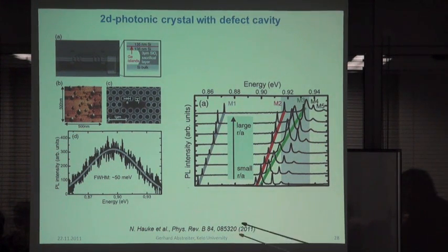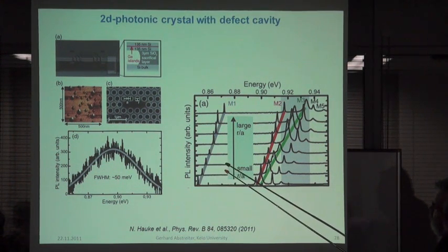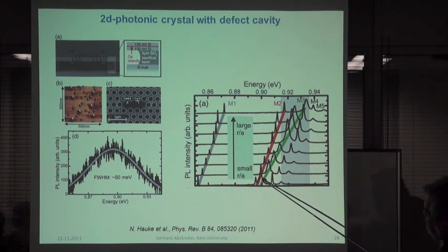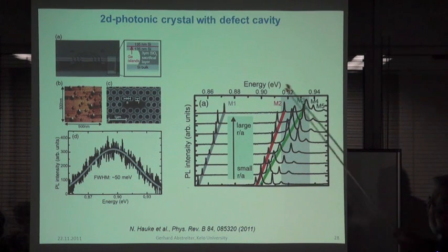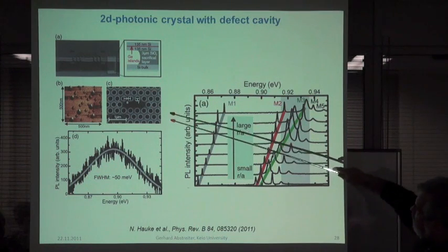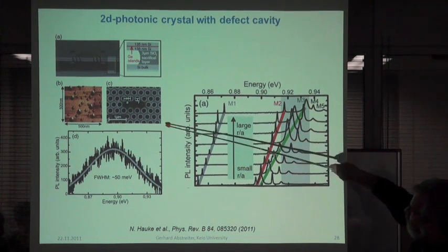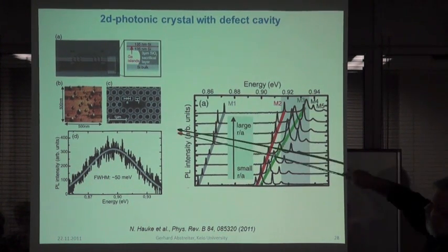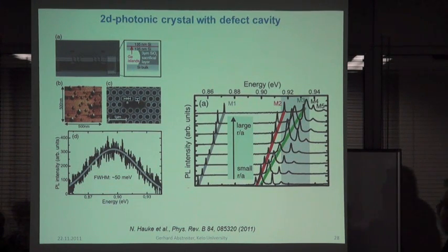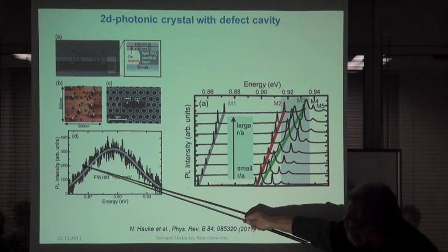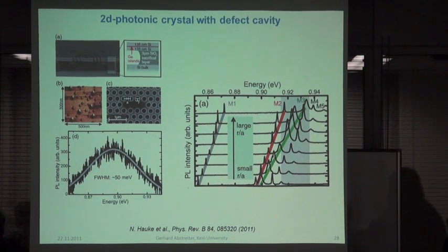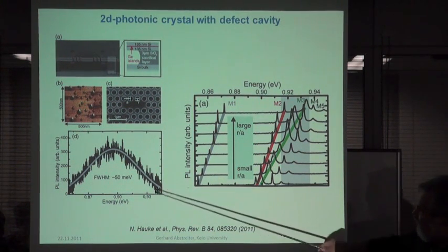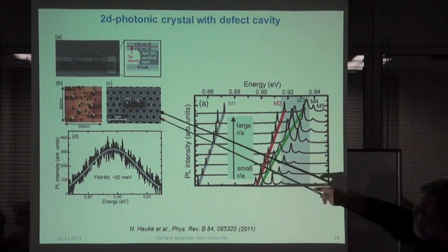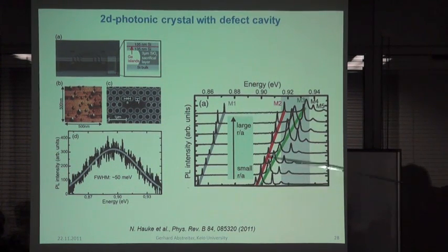Now, we did a very detailed study of this cavity effect. So what we tried to analyze is, this is just these modes on a background. Because this is a small scale, you don't see this broad background anymore. And these are the modes when we change, for example, the radius of these holes and keep the lattice constant a the same. This is what we measure with micro-PL outside, a very broad and weak luminescence with 50 millielectron volts, and this is what we measure inside this cavity, we get these modes.